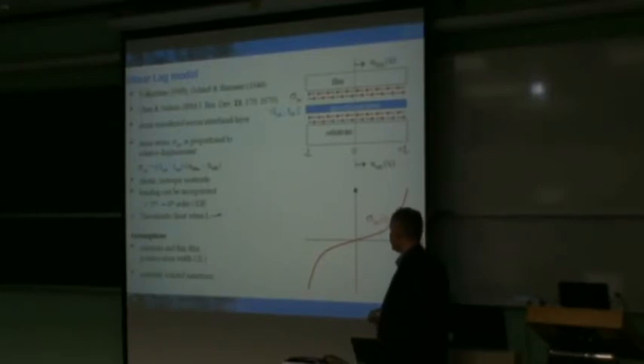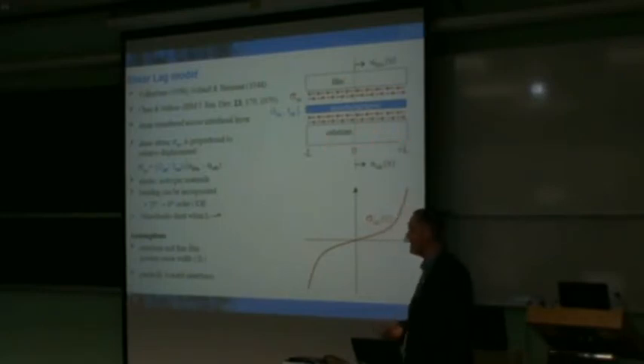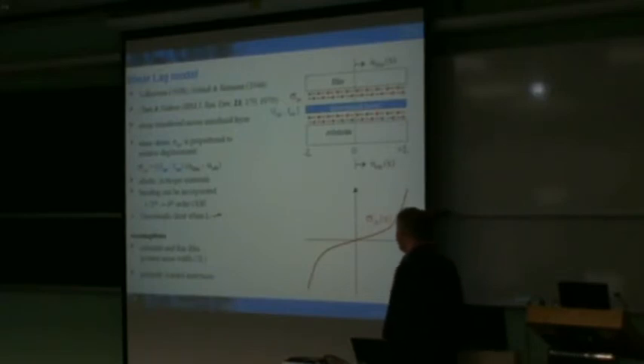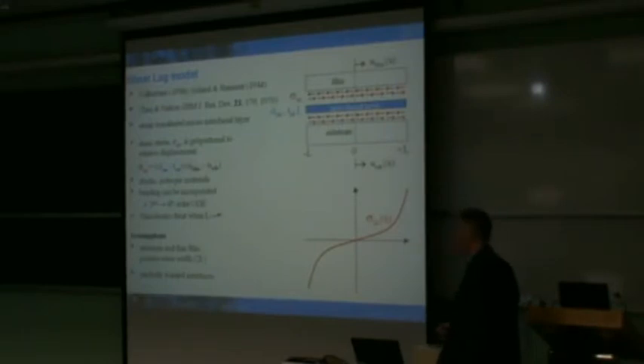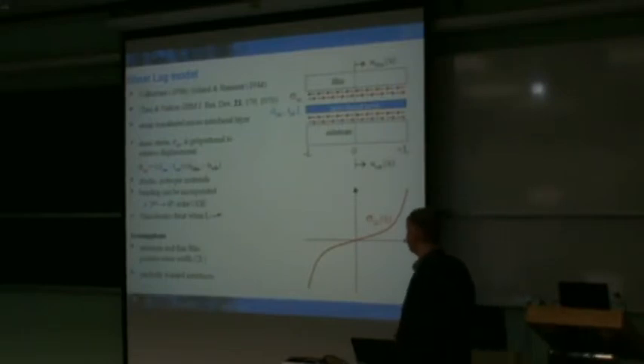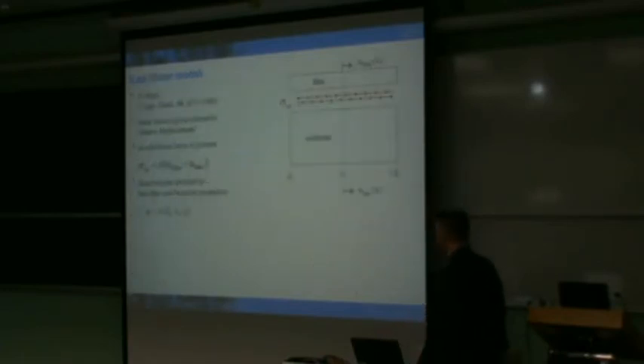One of the assumptions that I showed before in these types of approaches is that your feature size and your substrate dimension are the same. And that's really a key limiting assumption that is unphysical in some of these models. And I'll show why that impacts it. But also, we again assume that there is perfect adhesion here between the film and this interfacial layer and that of the underlying substrate. And that's a reasonable assumption for many of these structures. You can clearly expect to see different heterogeneous states of deformation here, but it's not necessary to look at the mechanical response of these systems.